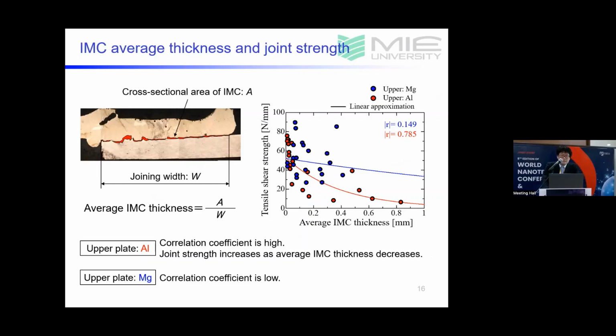In order to investigate the factors that affect joint strength, we focused on the intermetallic compound generated at the interface of joint cross sections. As shown in the picture, the cross-sectional area of IMC shown in the red region was measured and divided by the joining width, which was determined as the average IMC thickness. The graph on the right shows the relationship between the average IMC thickness and tensile shear strength.